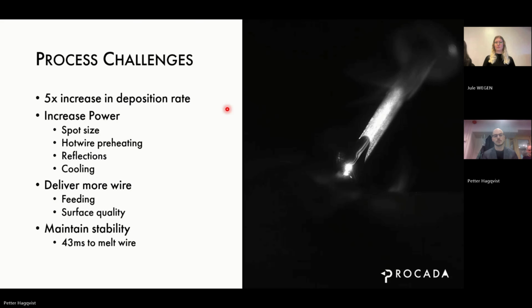And then there's also the issue of the surface quality, because the surface quality of the wire is both about any residue on the wire, and when we feed a lot of wire quickly, any residue will accumulate, and it might get the wire to stick in a nozzle and might not be properly fed into the process. But it's also a matter of, if we have a wire which has a poor surface roughness, then that will wear out a lot of equipment due to abrasive wear.